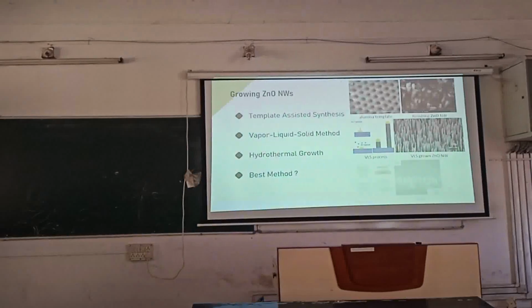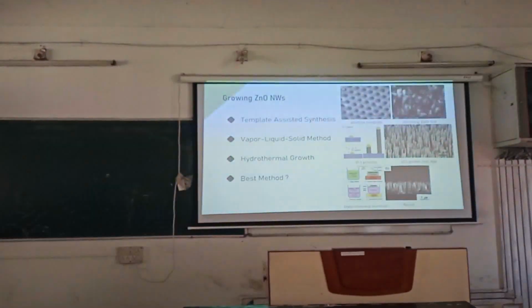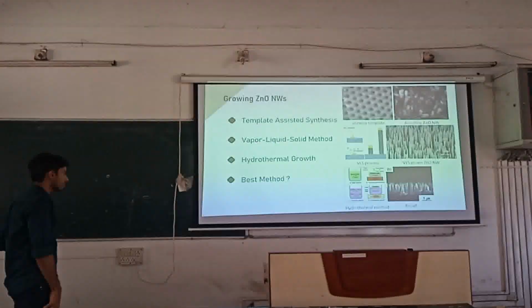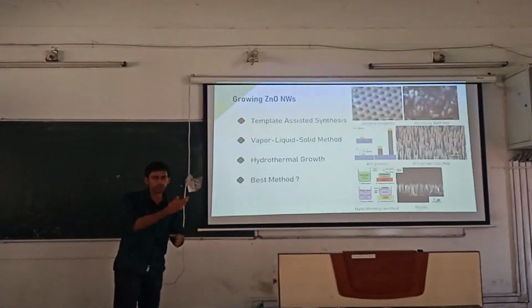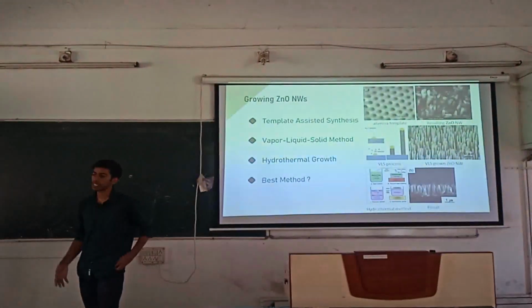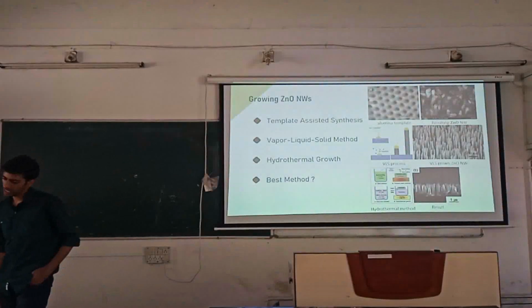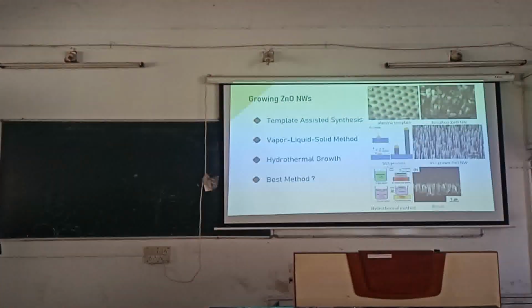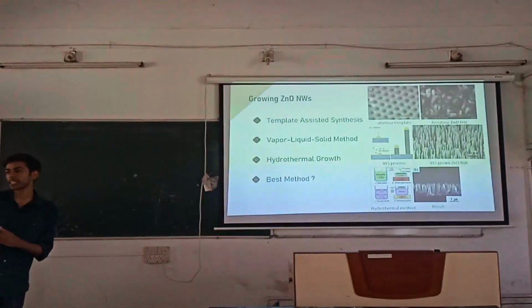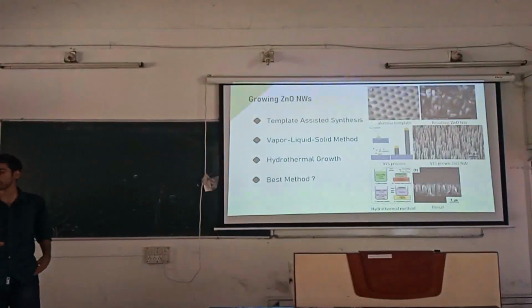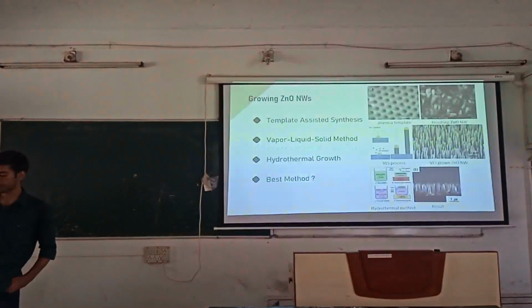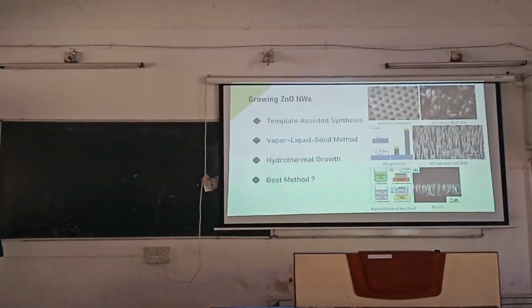So then there is a method called hydrothermal growth. It's a totally chemical growth method in which we use some chemicals, we put it in water, we wait for some time, and growth will happen. This is nice. This requires only temperatures up to 80-85 degrees Celsius, and the zinc oxide nanowires grown will be very close to each other, but by controlling how much chemicals we put, by varying the concentration, we can control the density of nanowires grown.